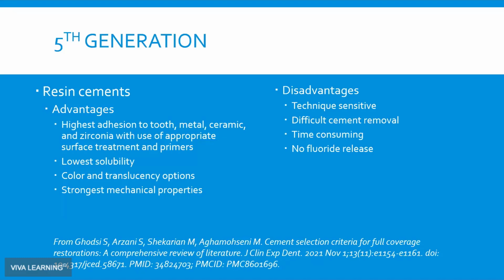But another factor was the cement removal. Oftentimes, if you didn't time the cleanup correctly, the cement would get so hard that no amount of use of the explorer tip or even a scaler would remove it. Now, I don't know, depending on the age of the listeners here, we had various saws and diamond strips and end cutting saws, and funny thing, I still stock most of those for the rare occasions that we need them. But the removal of the cement was no joke.